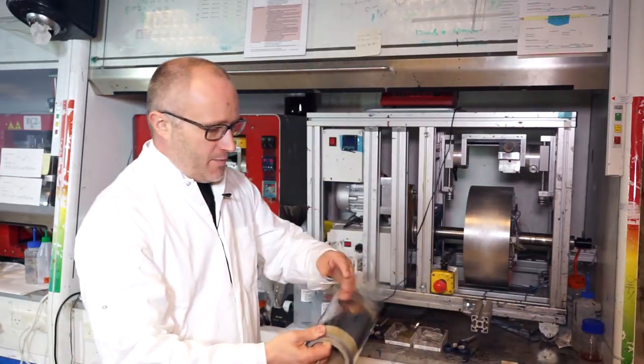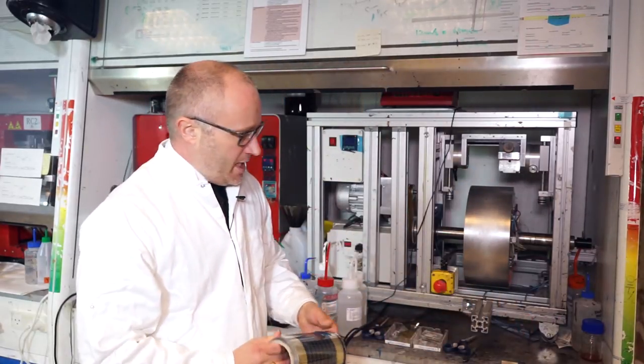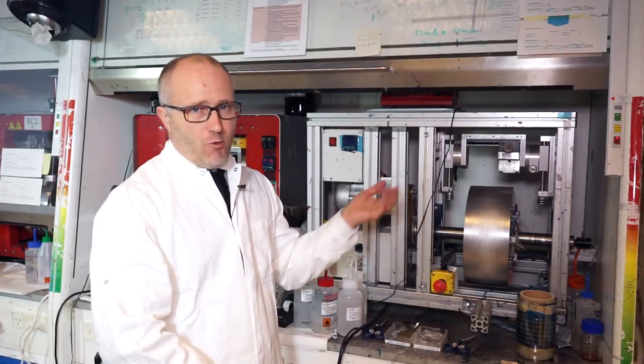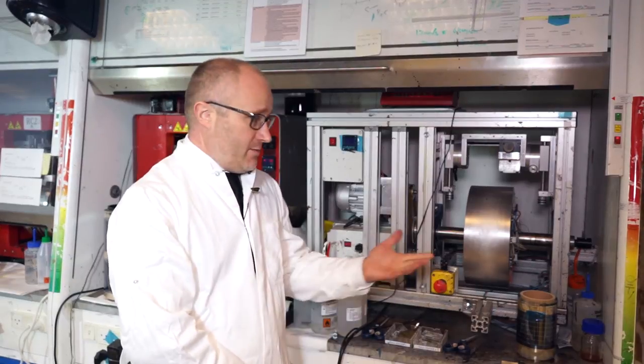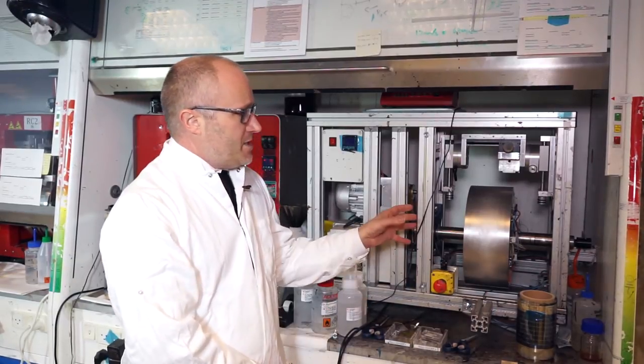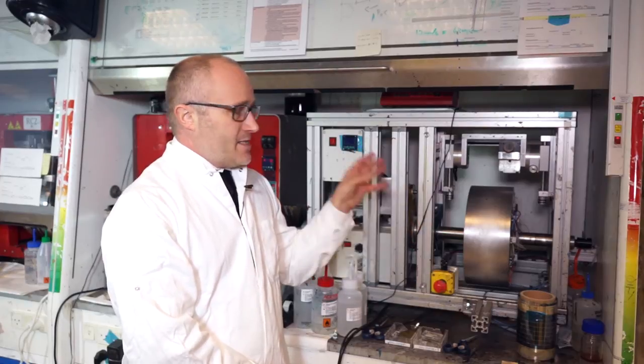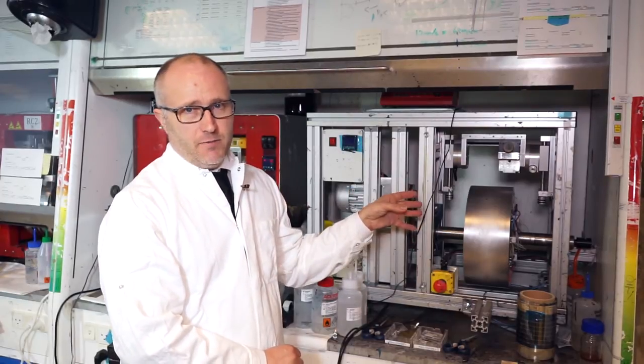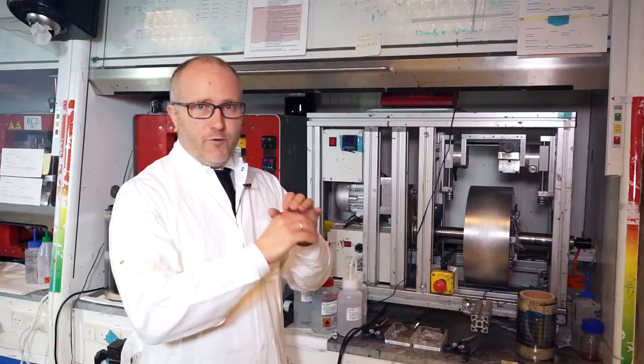And of course, being a metallic roll, an aluminum roll, it allows you to heat it up. So you can heat this roll to a temperature, of course, that is sustained by the substrate or the flexible foil. And the advantage here is that the static electric field is constant. So you get pretty close to the conditions you have when you spin coat. So you have no shear once you have deposited your wet film.